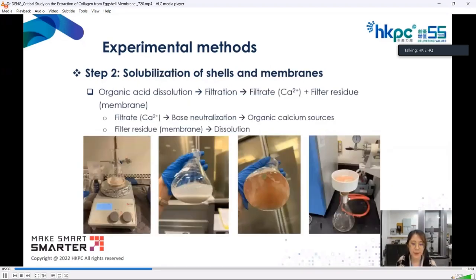The second step is to separate the outer shell and the eggshell membrane. In this study, an acid dissolution reaction was used. The eggshell waste collected from the centrifugal mill was washed with DI water to remove the remaining egg liquid. And then 10 grams of eggshell was mixed with 1 mol per liter acetic acid. The solution was stirred at 160 revolutions per minute until free of bubbles. Once the eggshell was completely dissolved, its membrane was collected as a filter residue.